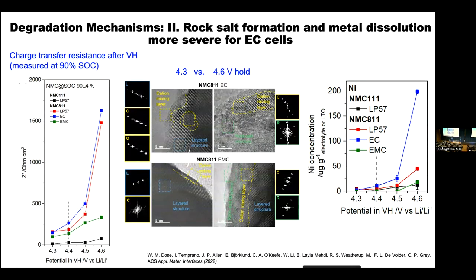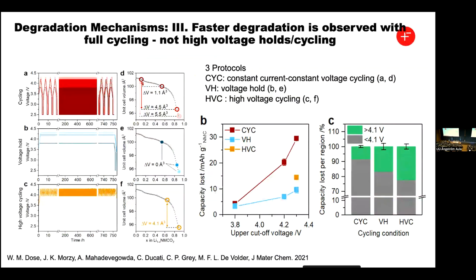You get this transformation of the surface layer from a layered structure to this rock salt layer, and then you can see also these intermediate half mixed layers between the two. All of these processes are much more prevalent in EC cells. Then he did something else that was quite clever, and that was to try and cycle the battery in different ways and decouple the different processes. So he did three things.